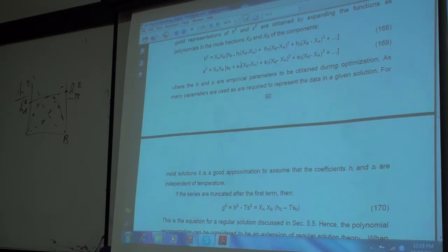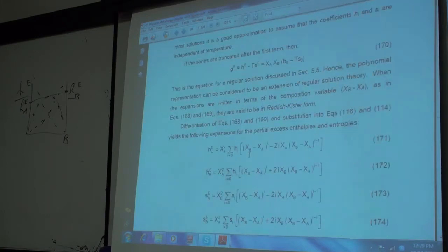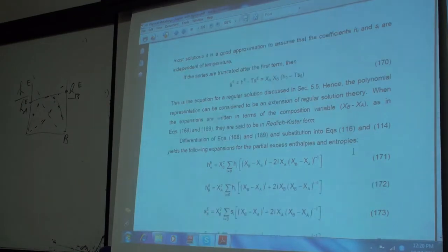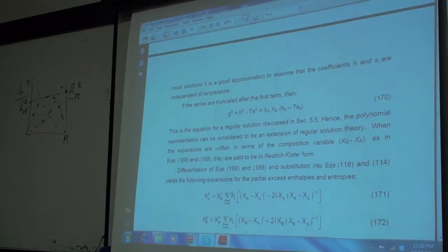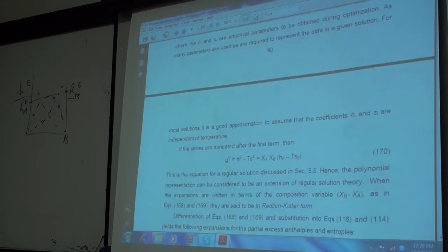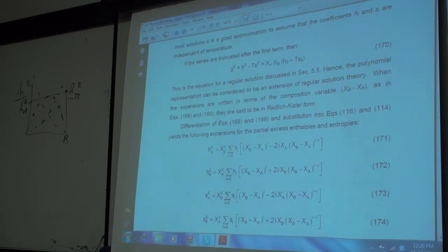So you have one set of parameters for the liquid phase, which will give you all the integral properties and the partial properties. Okay, so you need some sort of a mathematical least squares routine which permits you to simultaneously fit different properties to different equations, but those different equations have the same set of coefficients. I have some measurements of HXS which must be fitted to this equation, some measurements of HXSA which must be fitted to this equation, and some measurements of HXSB which must be fitted to this equation, but those three equations all are based on the same coefficients.